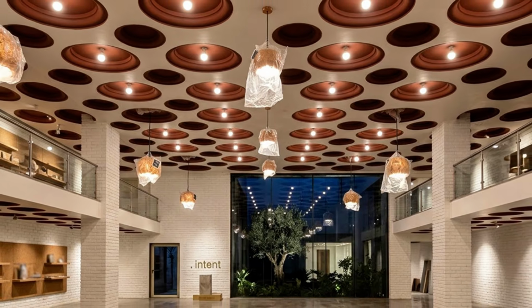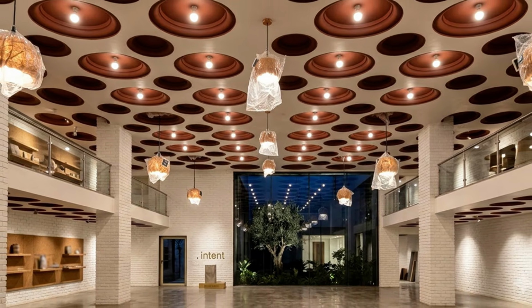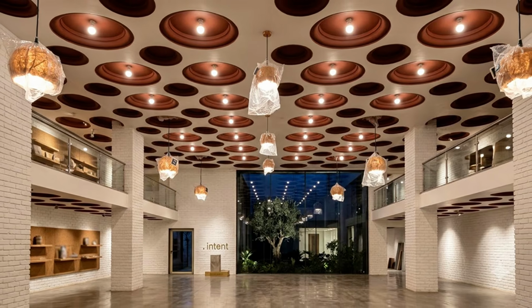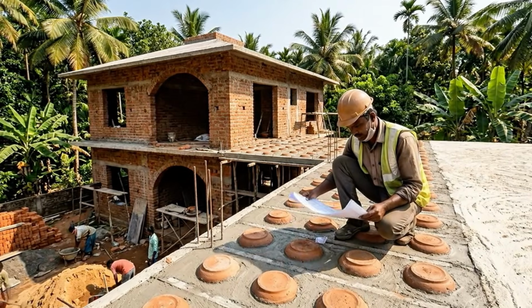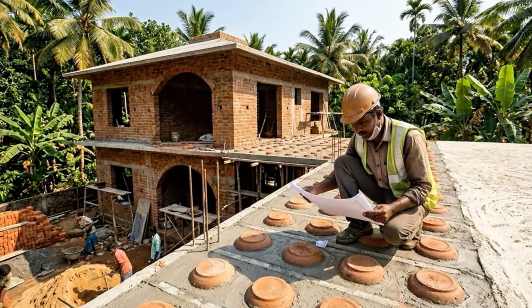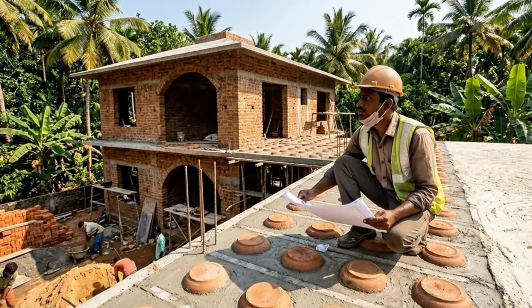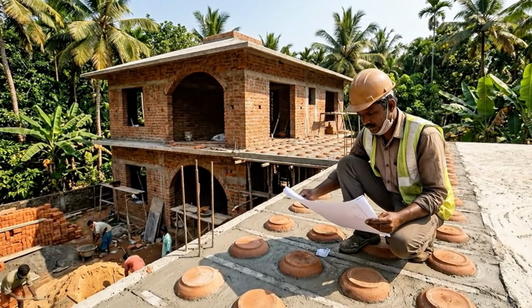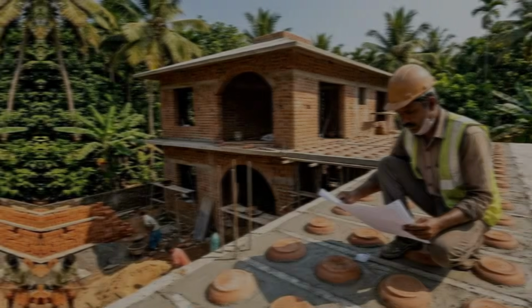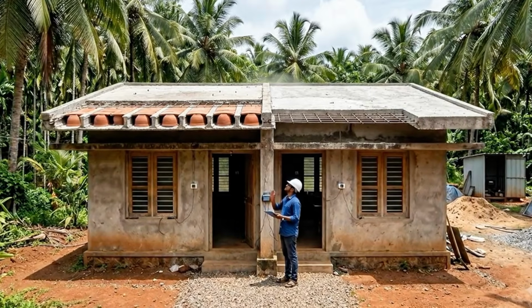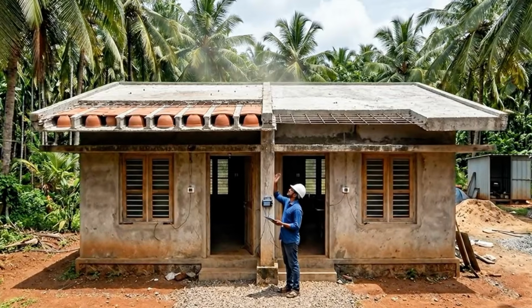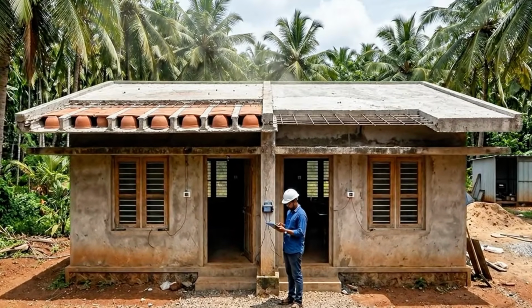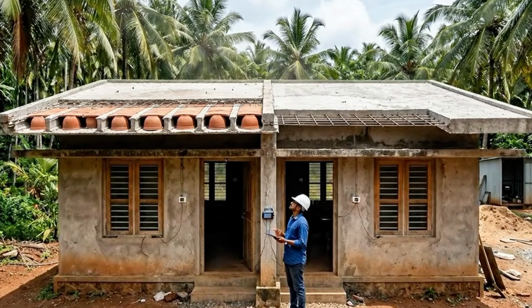And this is where many dramatic claims about clay pot roofs become misleading. A lower ceiling surface temperature is not automatically the same as an equal reduction in room air temperature. The result depends on the pot geometry, the thickness of the concrete, the roof finish, the amount of direct sunlight, ventilation, humidity, and the thermal behavior of the rest of the building. In one recent controlled comparison, a roof incorporating earthen pots reduced the room temperature by a little over 2 degrees Celsius compared with an untreated concrete roof.